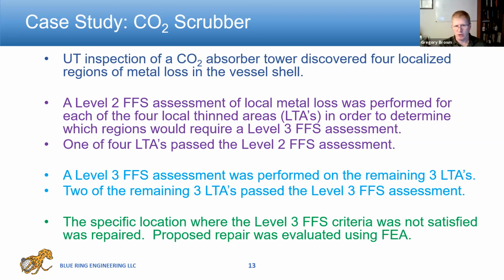Now, this kind of goes a little bit towards the question, which we can answer later. If on your equipment you have more thickness than your design minimum, you are covered under your code of construction and you do not need to do fitness for service. Fitness for service only occurs when my thickness drops below my design thickness, my T-min as it's called, and that's what causes a fitness for service. So in this case, there were 4 areas that had some thickness readings that were less than the required thickness according to the design code.